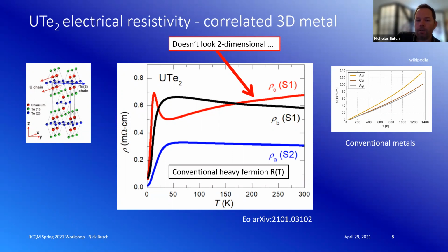Although it's a sharp feature here, there is nothing we can point to in the heat capacity, for example, that says this is a phase transition. So is it a crossover? Yes, maybe. What is its relationship to any putative heavy fermion renormalization? I'm not sure, because it seems to fall into the same temperature range. Separate phenomenon or tied to it, I can't say definitively. Is it sample dependent? To the best of my knowledge, maybe the magnitude is, but transport experiments have been difficult to quantify. Questions could always be about misalignment or contact quality, so I can't really speak to the statistics of that yet.